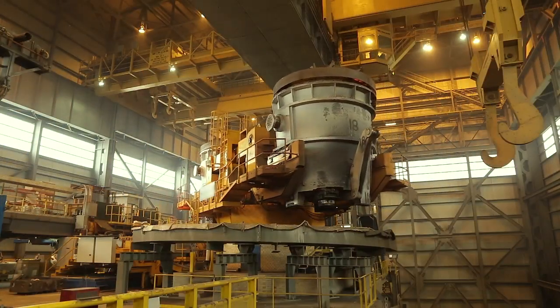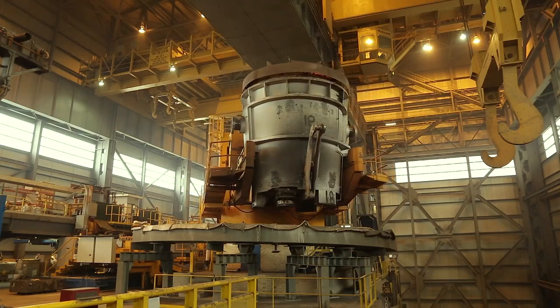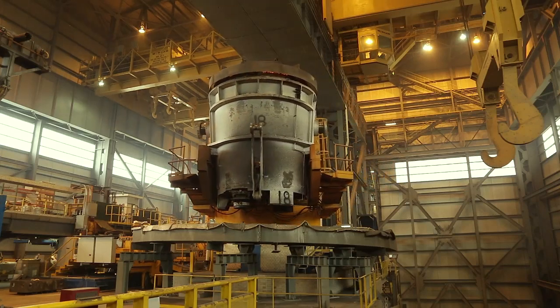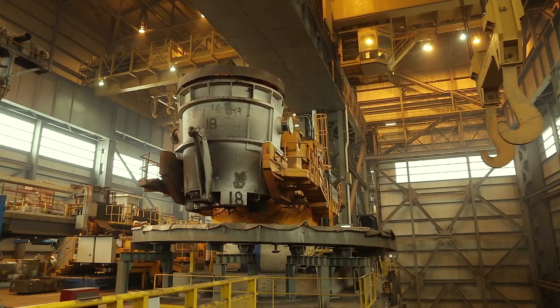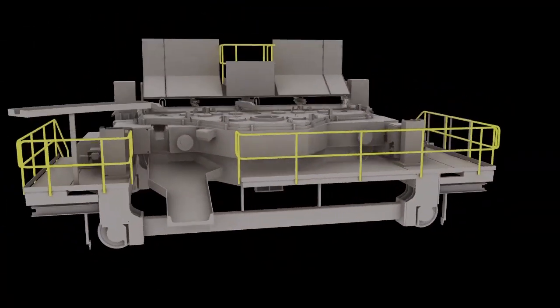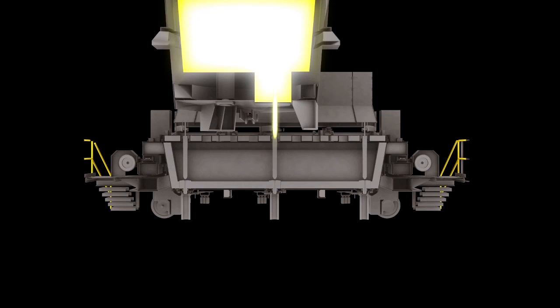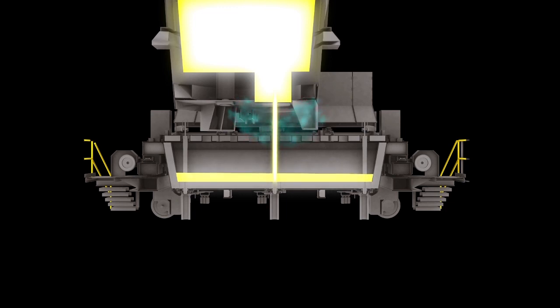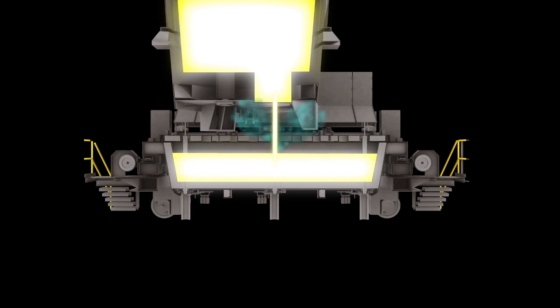Once the ladle is ready to cast, the turret rotates the ladle over top of the tundish. When the ladle reaches over the top of the tundish, a refractory valve opens to allow steel flow from the ladle into the tundish. During this process, a physical shroud and inert gas protect the steel stream from oxidation. As steel flows through the tundish, a series of flow modifiers control the flow, allowing for optimum inclusion flotation and steel cleanness. The steel then exits the tundish to each of the 3 strands.